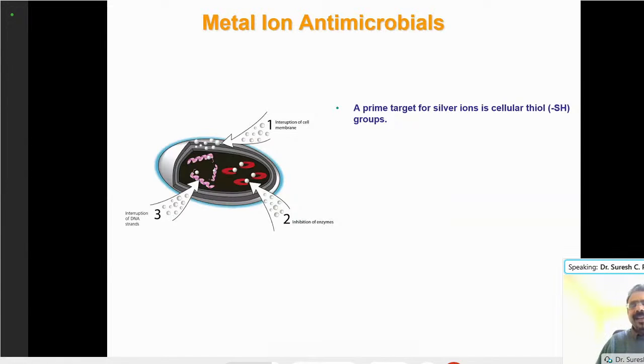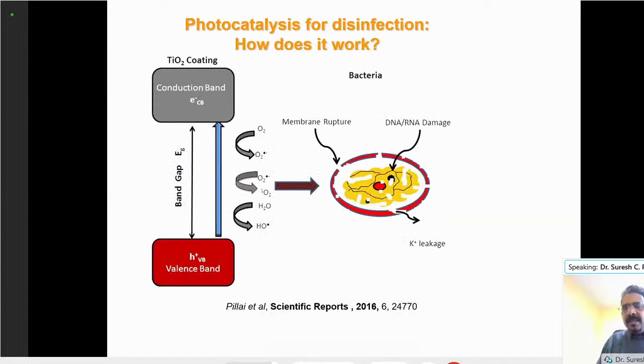But the problem is that the debris after the killing of the bacteria will still remain there, and eventually a lot of debris can form on the surface. But the beauty about photocatalysis is that we can remove the debris as well, or the toxins produced after the death of the bacteria can also be removed by photocatalysis, because photocatalysis is a continuous process. It's a molecular process. It attacks the biomolecule. So it keeps on working until the simpler molecules are formed. So photocatalysis is a very effective mechanism for disinfecting the surface.